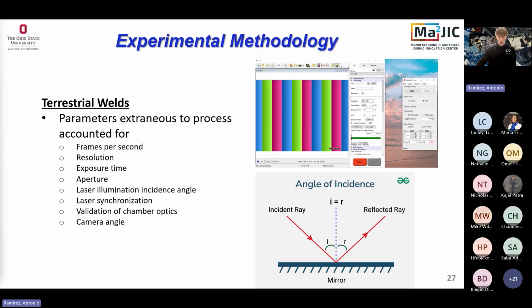So for terrestrial welds, there are a bunch of parameters we had to account for. So frames per second: what frame rate would we need to get optimal data for our model calibration; our resolution; our exposure time, or how much light is exposed to each frame; our aperture opening, which is more to do with the lighting; and our laser illumination incidence angle, which is the angle that the laser is pointing towards the viewport at.